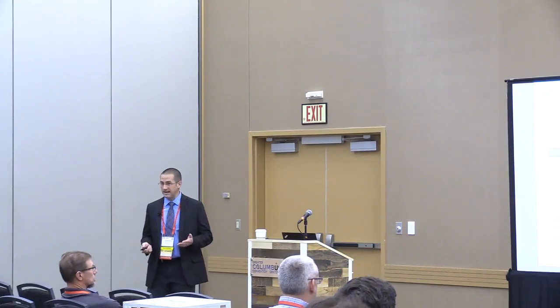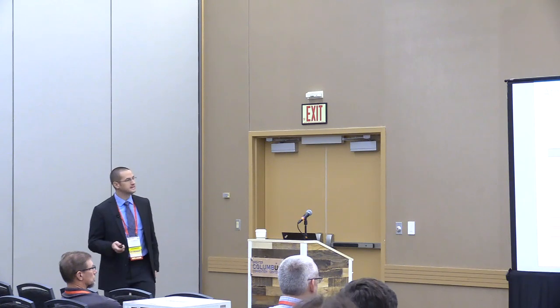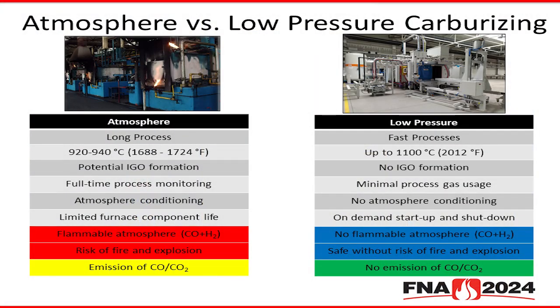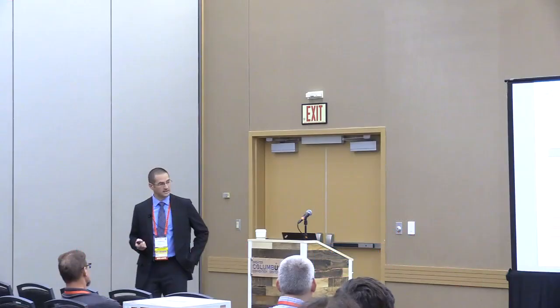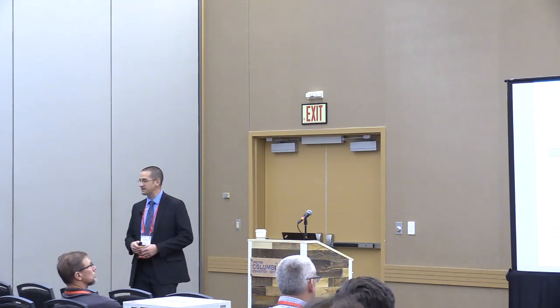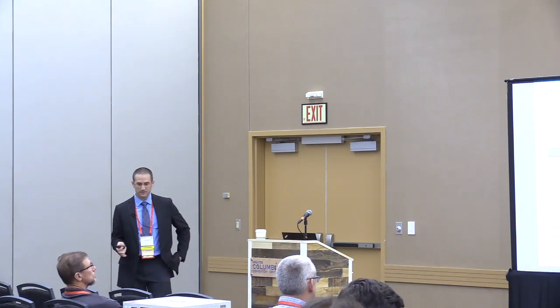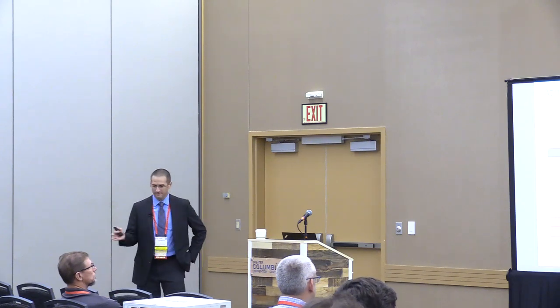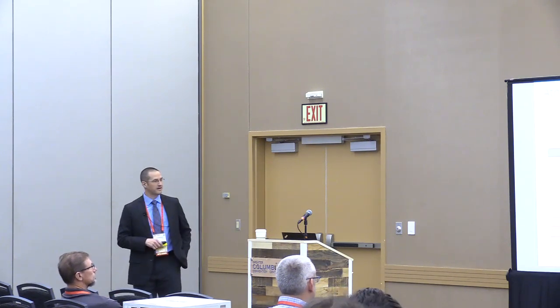There's minimal process gas usage with each run. No atmosphere conditioning. The furnace is off when we don't need it. It's on when we do need it. We don't need to continue to run the furnace, which also helps with the fact that we don't have to wear the furnace when we're not using it. Also, because there's no oxygen in the furnace, there's no real risk for a flammable atmosphere, and because of that, no risk of fire and explosion.